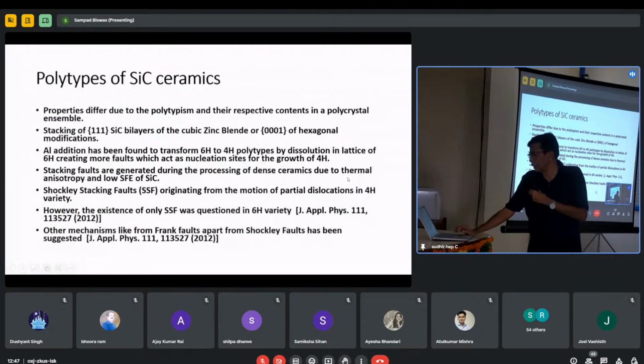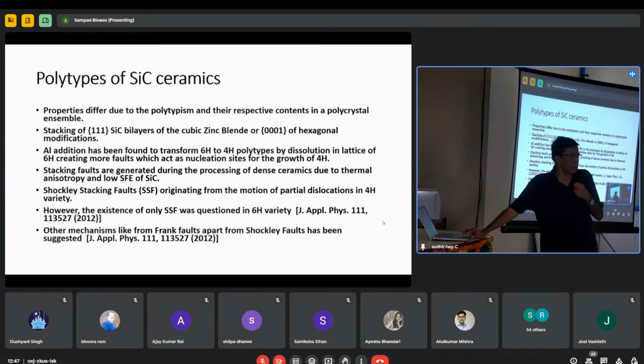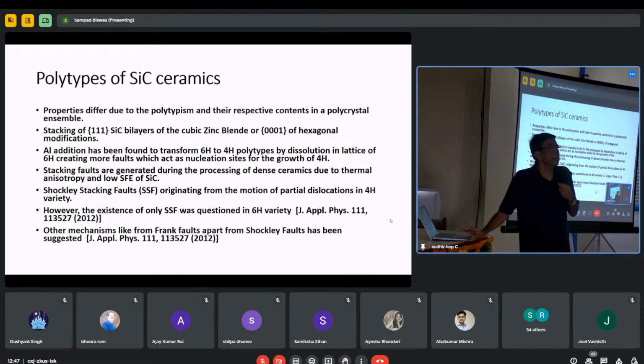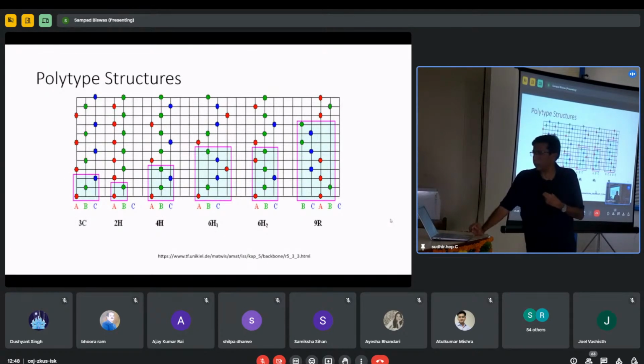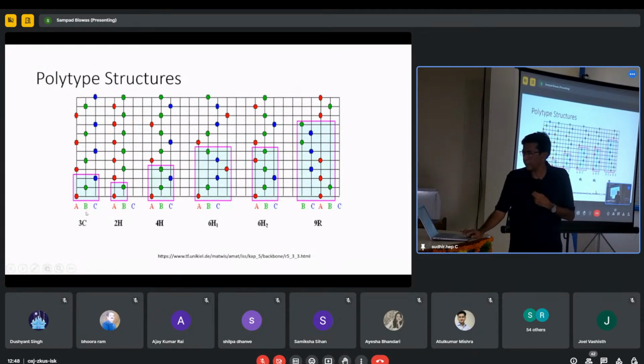So there is the existence of Shockley stacking fault. Somebody may question whether Shockley stacking fault is the only stacking fault, but Frank stacking faults are also present in this material. Now let us see how the polytype structures are. You can see this is the pure 3C. These are the 3 stacking layers A, B, C. Then this is the 2H. Then this is the 4H. You've got 4 layers. There is 6H. You have got 6 layers, and so on and so forth.